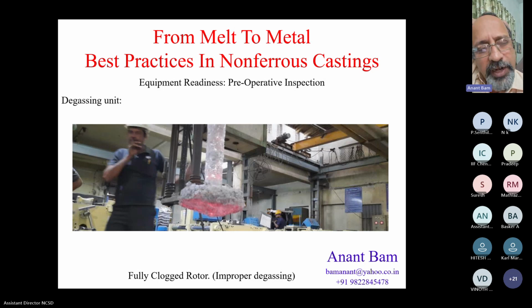Again, it's first-hand information. I was a consultant there. I was called in because degassing was not effective. Even after doing degassing for 2 hours, our density index was not coming within the range. Kindly advise us. And the matter was solved at the first visit itself. If you have got such a dirty rotor, nobody on this earth can degas your material. The best way is to change the rotor and then onwards maintain the rotor in good condition by cleaning it every time it comes out from the furnace. Next slide, please.